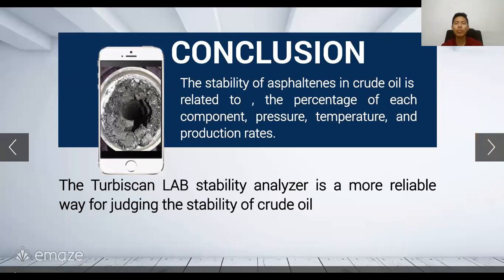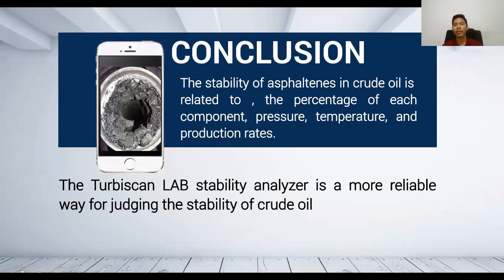In conclusion, it was understood that asphaltene molecules in the crude oil are stabilized by resin molecules, preventing the deposition of the asphaltenes, but also the study of the crude oil composition, which are saturates, aromatics, resins, and asphaltenes, demonstrates that the stability of asphaltenes in crude oil is a phenomenon that is related to the components' behavior, the percentage of each component, the influence of each fraction on other fractions, and also taking into consideration the changes in the pressure, temperature, and production rates. But it cannot be associated with only one of them individually.